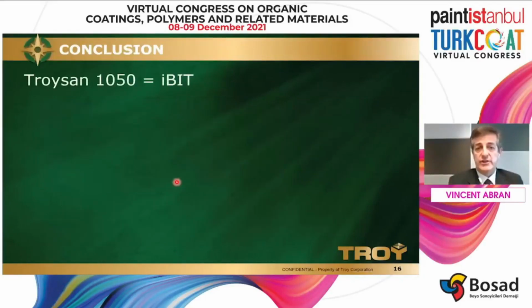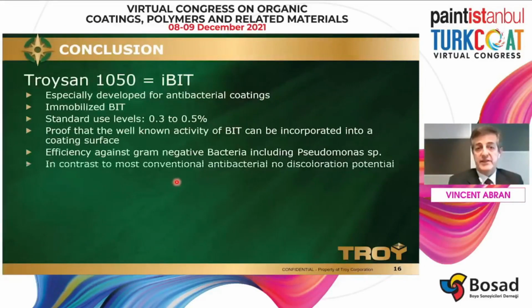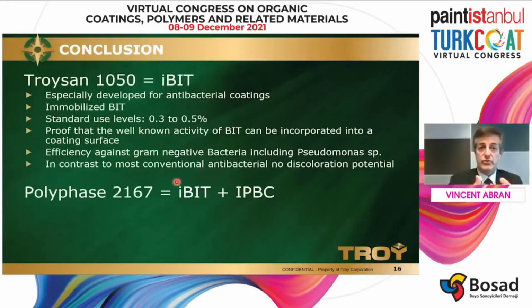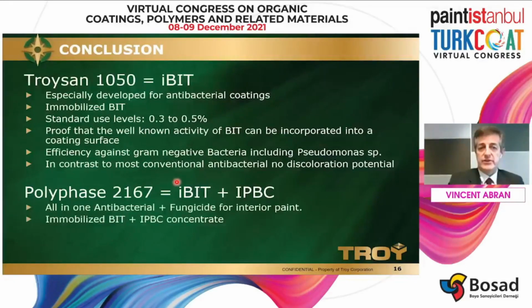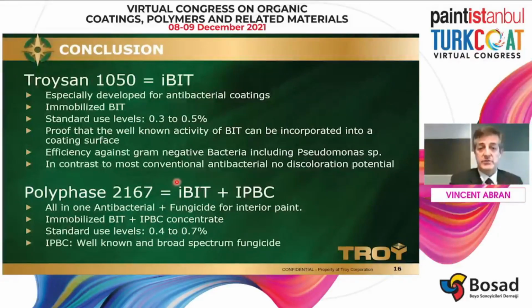So now, as a conclusion, we have immobilized BIT available as such. If you just want to enhance your product performance with additional antibacterial performance, normally we say between 0.3 to 0.5% to have at least 500 ppm immobilized BIT. The next option, if you want to have a complete protection of your coating or a product in general, is to consider an all-in-one antibacterial and fungicide for interior paints, for example, or any other application which requires the same protection. And then you have immobilized BIT plus IPBC combined together for complete protection. And normally we say between 0.4 and 0.7%.